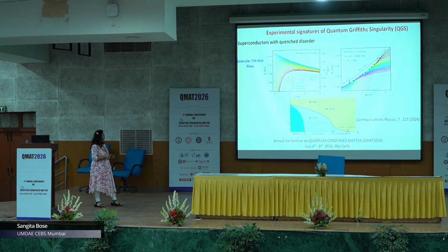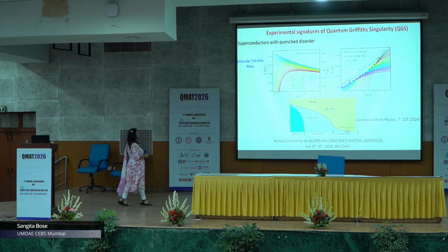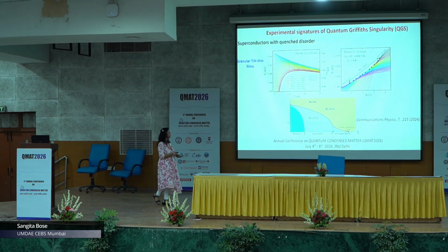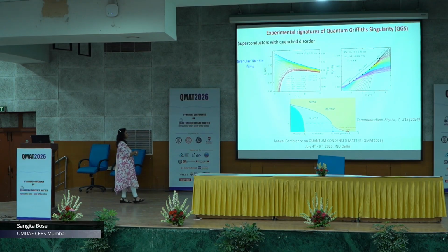So now if you go to this result in granular titanium nitride thin film, again, this is a magnetic field tuned superconductor to insulator transition. So, you change the magnetic field and you go from a superconductor to the insulator. But now if you look at these magnetoresistance isotherms, you see very different behavior than what I showed you in the previous slide. Here you just do not have a single crossing point.